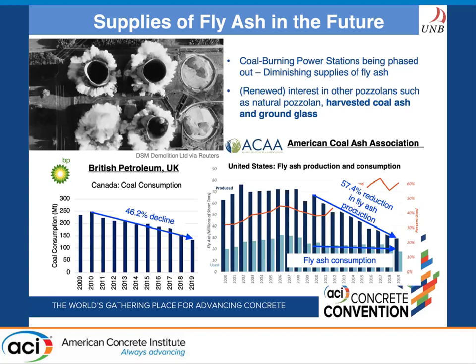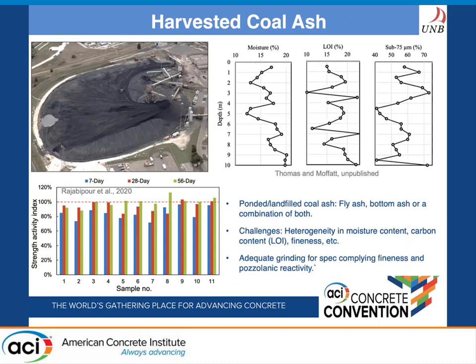In this presentation, I will mainly focus on harvested coal ash and ground glass. Coal ashes that were not used in concrete or other applications and were stored in ponds or landfill sites could now be used as a concrete pozzolan. However, there are certain challenges. The main challenges in using harvested ash in concrete are moisture content, LOI, and fineness, because these properties vary significantly even within a source, and may vary a lot from one source to another. The ash in ponds has weathered over time and could be a combination of fly ash as well as bottom ash.